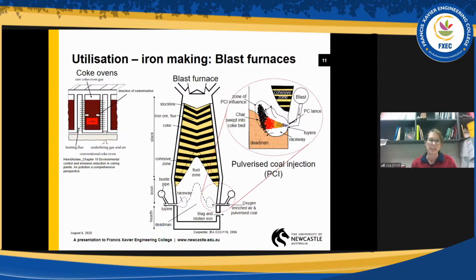and it does reach the end of the raceway, it has potential to block up the rest of the bed because the gas has to travel through that bed to get out. And if you block the rest of the bed up, you don't get gas travelling through, you don't get reduction. So that is the big issue for PCI. For coke, if you can't make a coke of good strength, the bed will collapse and you again won't get gas flowing through your bed.